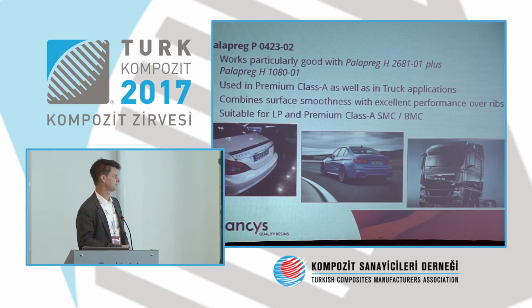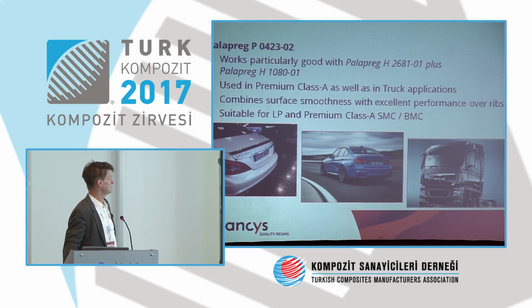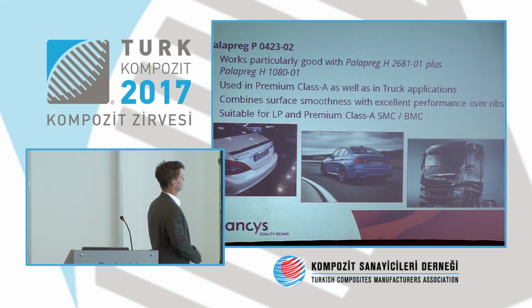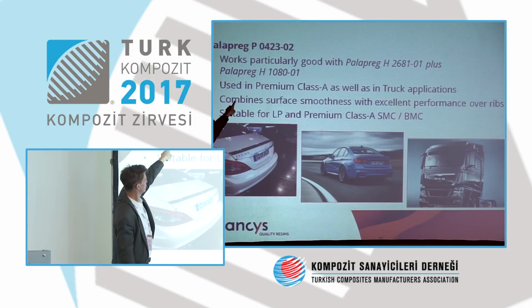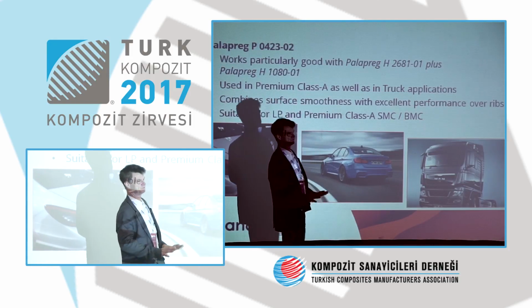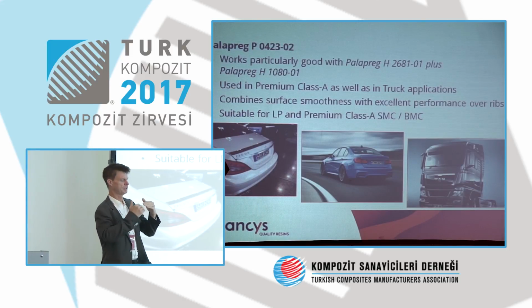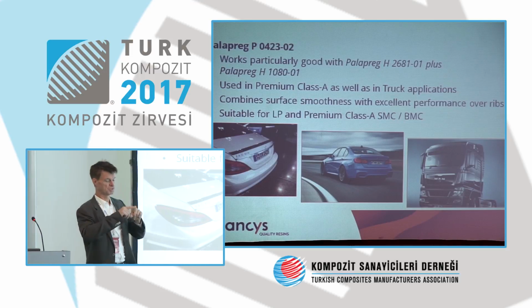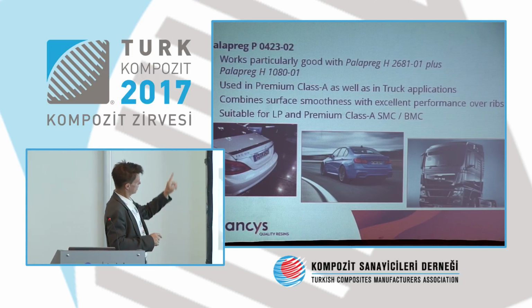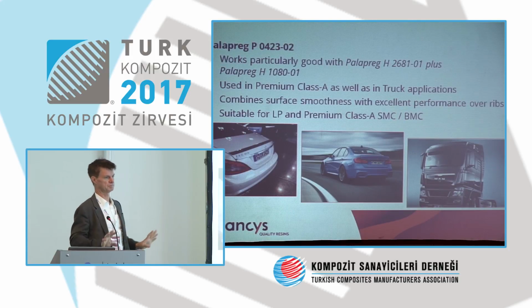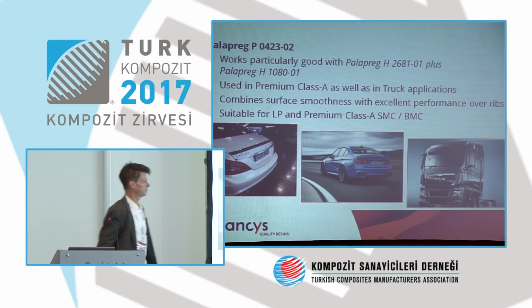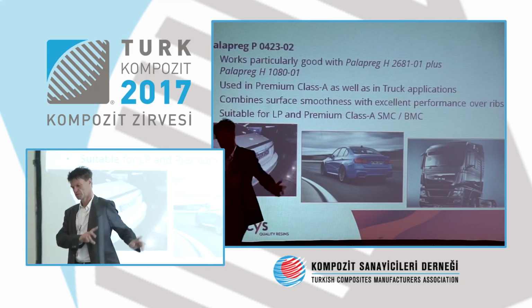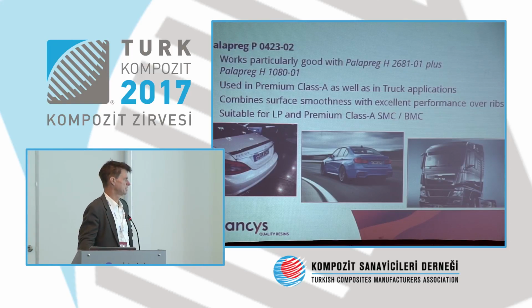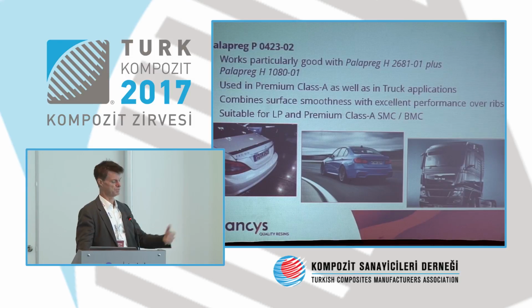With all these positive results. In the truck industry, it's basically used because with a combination of 0423, Palapreg, and 2681, you have excellent performance above a rib. Because typically when you have a rib inside, you see some sink marks after molding. And by using this, it is almost eliminated. You cannot see it. You cannot see the rib anymore. And therefore, if you go, for example, for a bumper where you have ribs behind, you need a stiff element. This one is excellent in performance, and you cannot see it from the front. There are ribs behind.